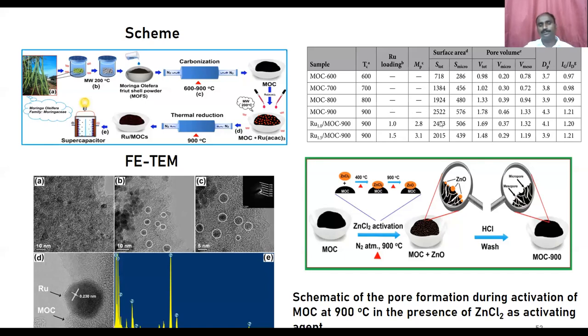After doping the ruthenium nanoparticles, the total surface area is somewhat reduced, because the ruthenium nanoparticles are doped on the porous carbon material. That's why the surface area is somewhat lower compared to the bare nanomaterial. I prepared the material with a higher surface area, nearly 2522 square meters per gram, and a total pore volume of 1.76 cubic centimeters per gram. This type of material is helpful for supercapacitor or energy storage applications.